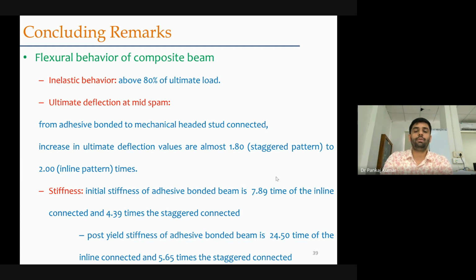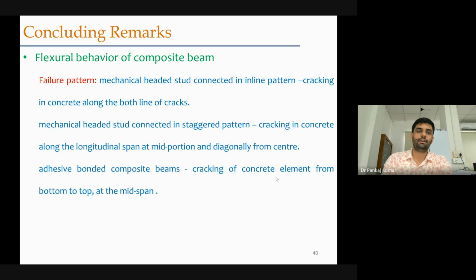So that is quite high. And when we compare post yield, that is about the ductility, we can take it as a positive aspect as well as a negative aspect. When we look into the long term, or in terms of energy, it is kind of negative. The post yield stiffness of adhesive bonded was 24.50 times in comparison with inline, and 5.65 times in case of staggered connection.